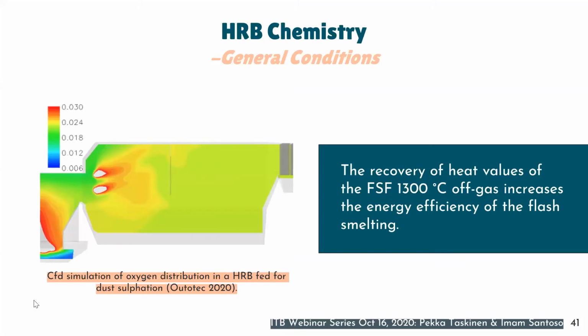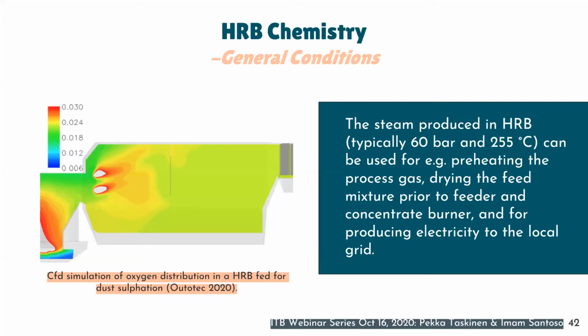And this heat recovery boiler is a big hollow device where oxygen is added to the cooling gas, and when the temperature goes down, it causes some oxides to be converted into sulfates. So the heat recovery boiler was introduced in the flash smelting line for capturing the heat values, which it converts into steam, and that steam can be used for heating purposes, drying the feed mixture, or generating electricity to the local grid.